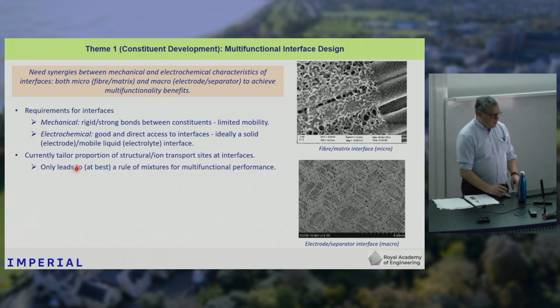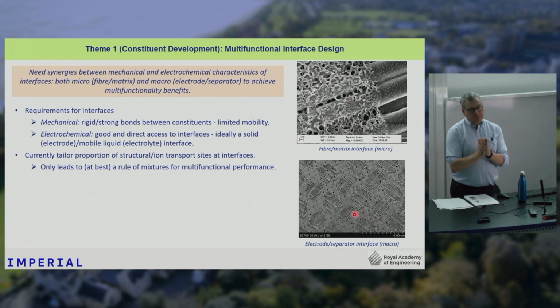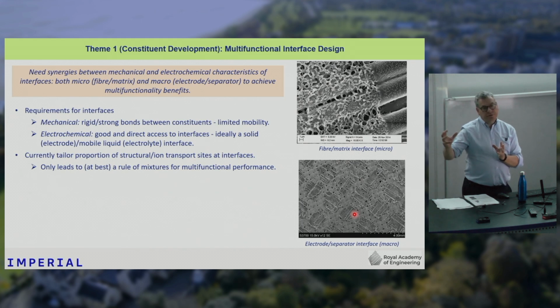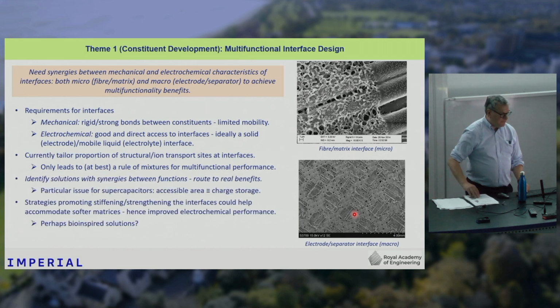We want to design the interface at the fiber matrix level. So this is showing you some carbon fibers with a multifunctional matrix on the surface. But also you have the interface between the electrodes and the separator. And again, there's conflicting requirements there. That interface needs to allow ions to move across it, but it also needs to be rigid to carry mechanical loads. So these are two aspects that we're very much focusing on at the moment, trying to address that.